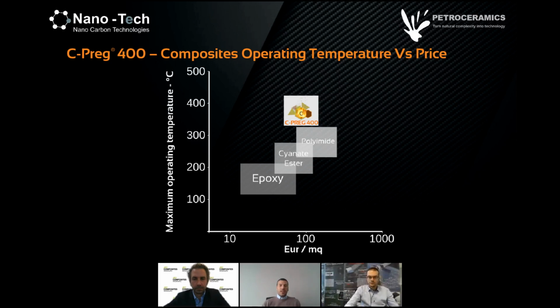Compared to the other organic composites, we offer a significant advantage, which is very high thermal stability. We say up to 400, but it can go even higher for a short period of time, maintaining the shape. The highest Tg on the market, even higher than polyimide. And we also have good drapability and workability, so you will not have the issues you may have with other prepregs. And also, as we said before, it is safe to use, as it is not made with phenolic resin, polyimide, or other organic resin.